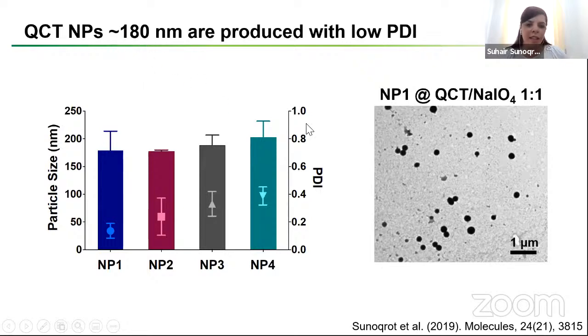It was 180 nanometers. And it depends on the ratio. They had moderate to very good polydispersity index. The best one was NP1, where the ratio was 1:1 between quercetin and the oxidizing agent.